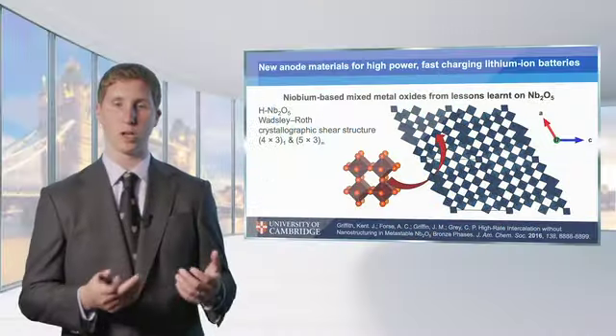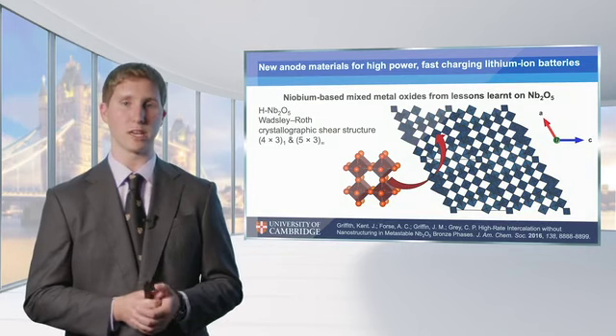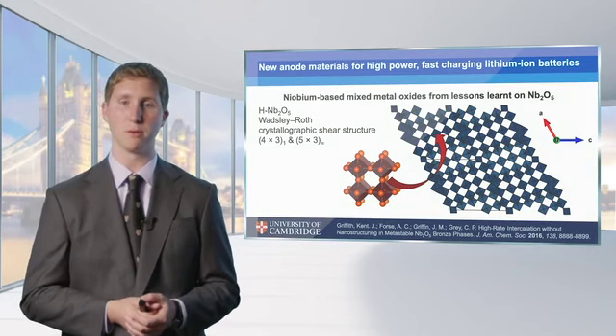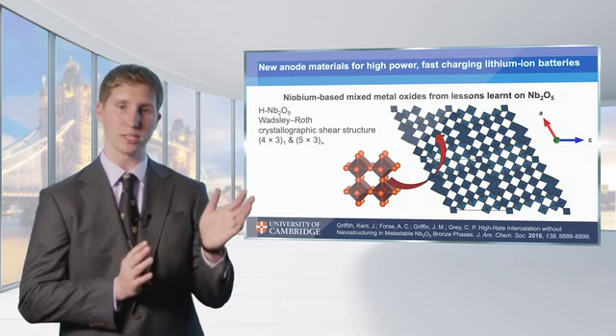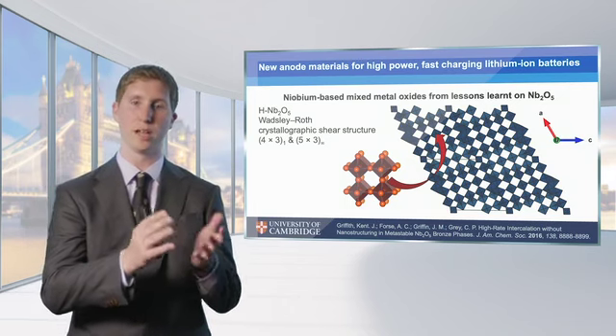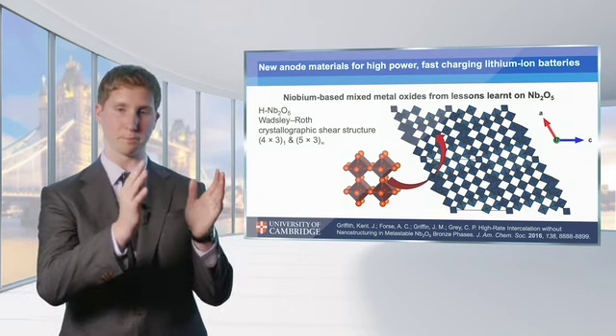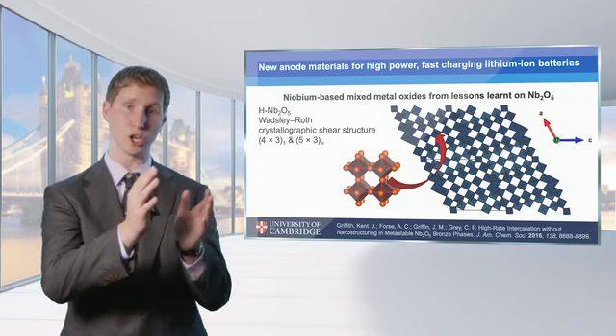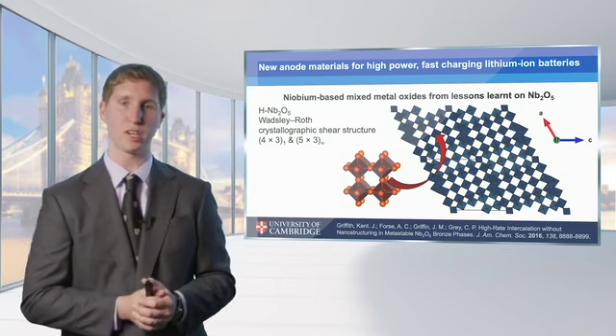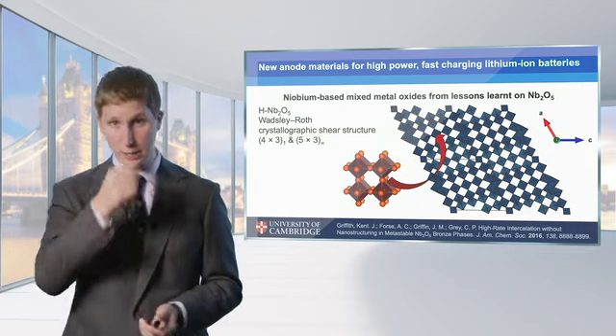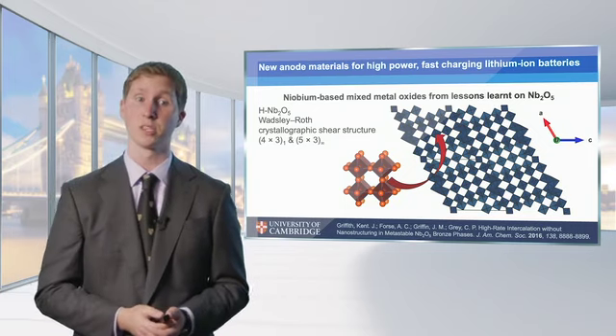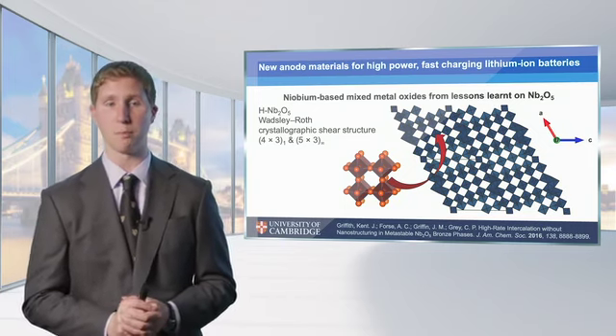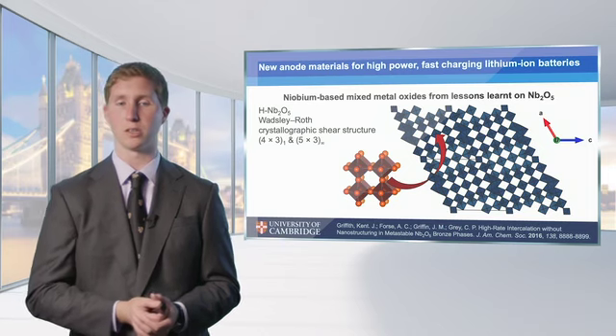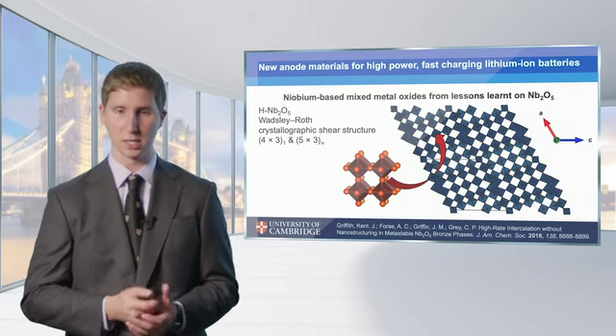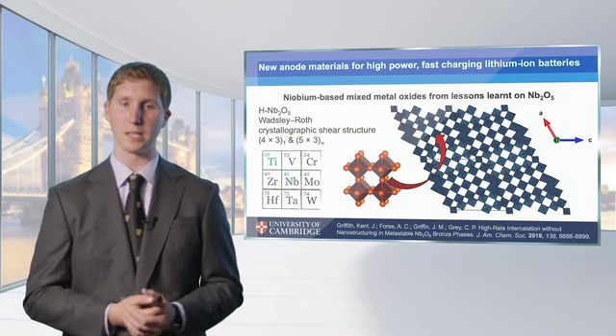And so there are different ways that the defect chemistry could adapt to overcome this, but in the shear structures, those planes shift with respect to one another, and so you go from fully corner sharing to some edge sharing sites. So the structure effectively condenses into blocks, and these blocks can take different sizes. So in the polymorph of niobia, we have two different block sizes.